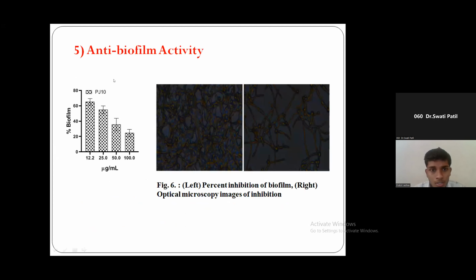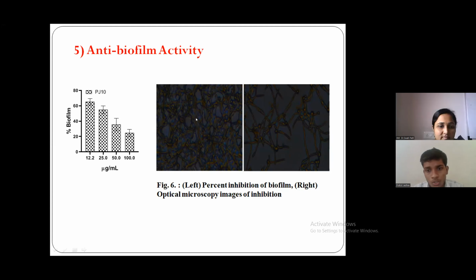Then, as I told, the copper oxide nanoparticles were further tested for anti-biofilm activity. Here the nanoparticles worked as an inhibitor that inhibits the growth of Candida albicans, which is a fungus. The left image shows the percentage inhibition of biofilm, and the right image shows the optical microscope image of inhibition. And here is a plot of the percentage biofilm inhibition.